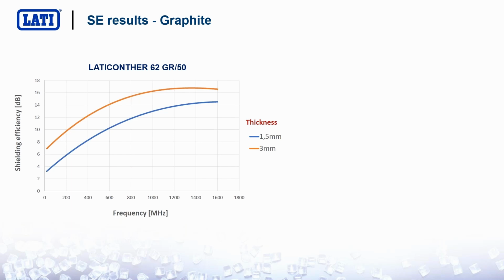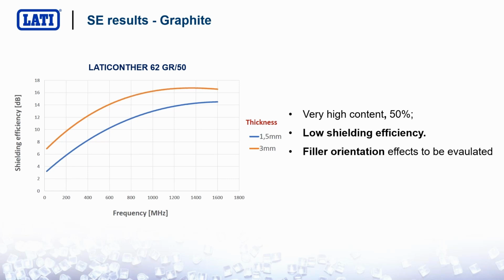Fourth experiment, graphite. What happens with graphite? Very poor shielding. I must say that this graphite is suitable for thermally conductive applications. We used LATICONTHER, which is a thermally conductive compound, so maybe it is not the best graphite for EMI shielding, but we saw a very slight improvement, very low shielding efficiency. For sure, the filler shape, orientation, and dispersion was not optimal.